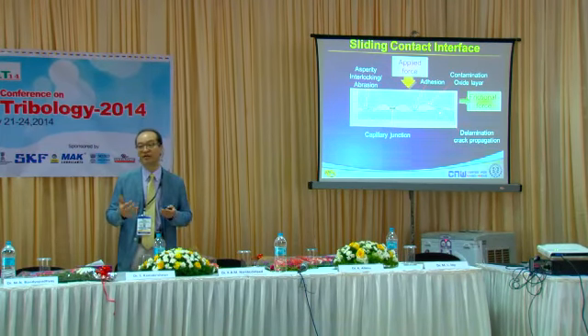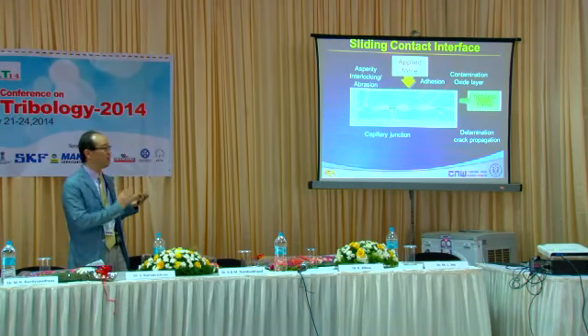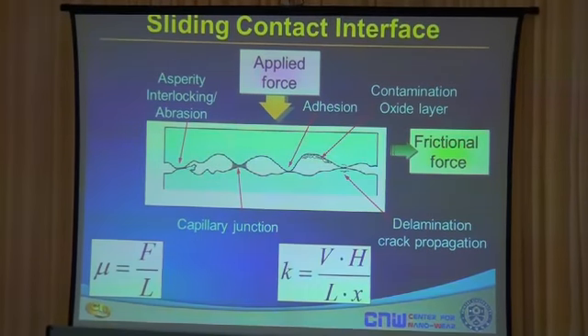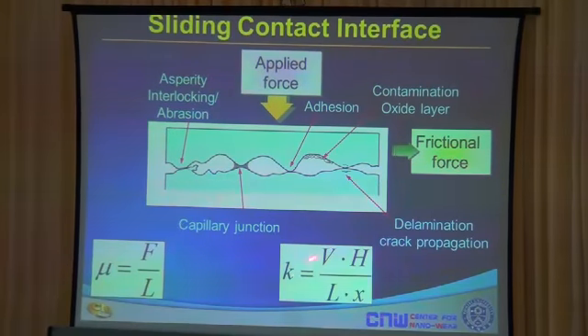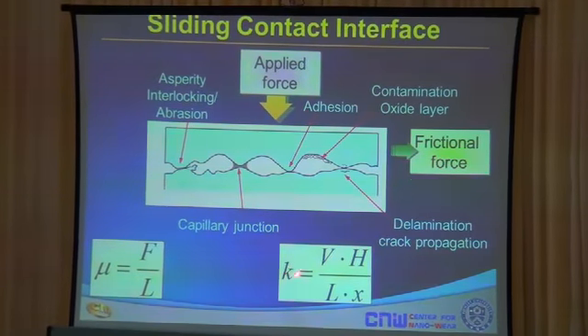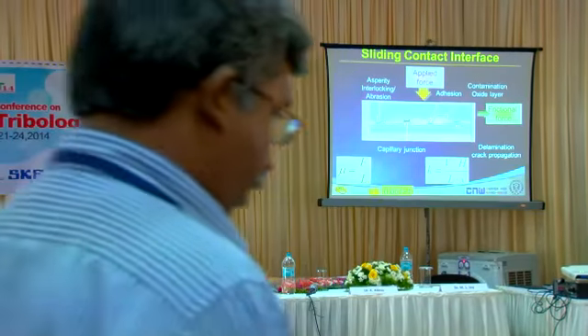So all these very complicated phenomena are going on at the interface, and we have to be able to control this. In describing this very complicated phenomena, we use two coefficients, as you all know. First one is the friction coefficient, and the second one is the wear coefficient. Perhaps this may not be so familiar to you. Wear coefficient is defined by the wear volume times the hardness divided by load and sliding distance, represented by Archard's wear equation.